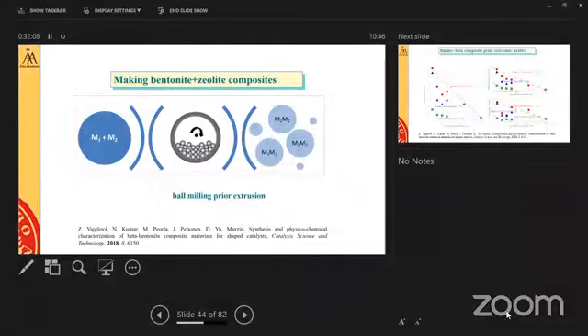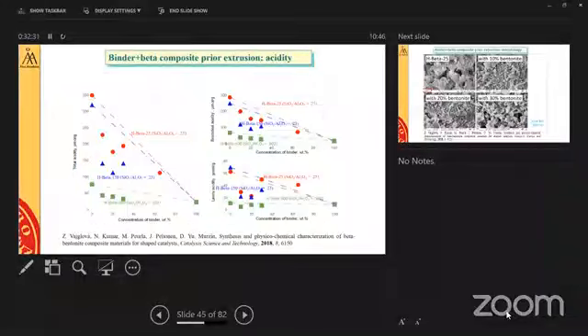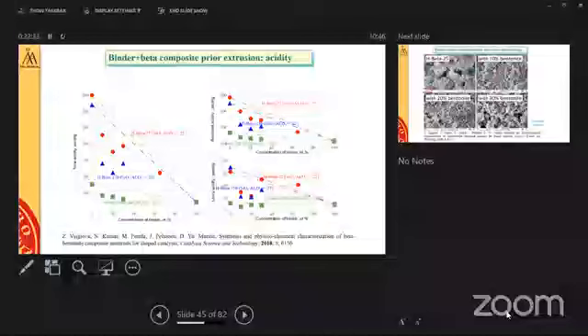Surprisingly, we were able to publish this paper 6 years ago in Catalysis Science and Technology, just characterizing what is happening when you mix the binder together with the zeolite. What would be your expectation? So there is certainly a mechanical force involved here when you do ball milling. So the classical assumption would be that there is no influence of this mixing on the properties. And the answer is no.